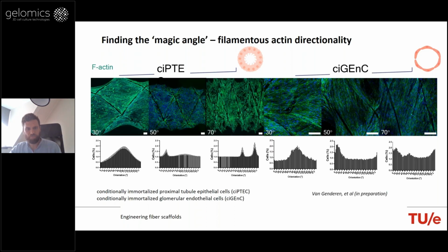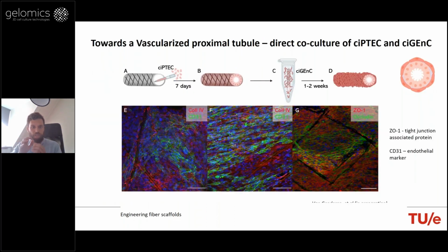And the difference between the three different angles, when you look at the confocal images on the right, was less pronounced when we cultured the endothelial cells. So it seems that there was no preferential alignment between the three different angles, although the 30 and the 50 degrees showed some sort of preferential alignment. And of course, these are preliminary results that we are investigating. And we also tried to combine an endothelial region with kidney proximal region at the center.